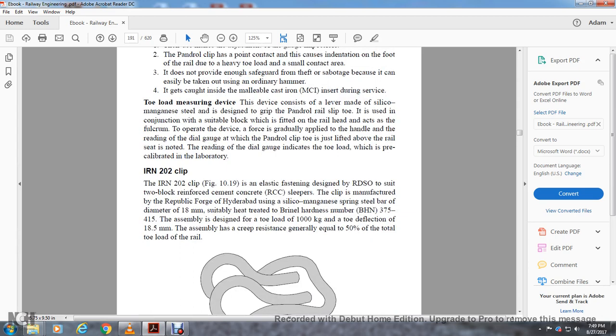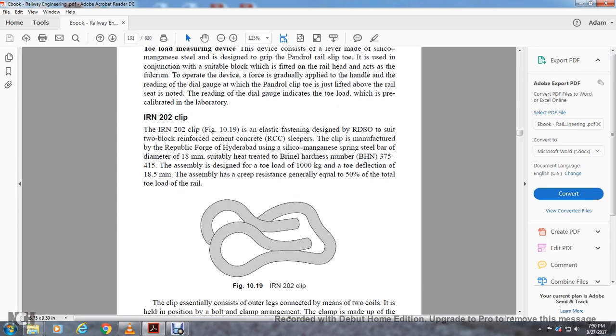Now the IRN 202 clip, an elastic fastener designed by the Research Design and Standards Organization to suit the two-block reinforced concrete sleeper, manufactured by Republic Forge with silico-manganese spring steel bar of diameter 18 millimeters, suitably heat treated with a Brinell hardness of 375 to 415. The assembly is designed with a toe load of 1,000 kilograms and total deflection of 18.5 millimeters. The creep resistance of the clip assembly is generally equal to 50% of the total toe load of the rail.